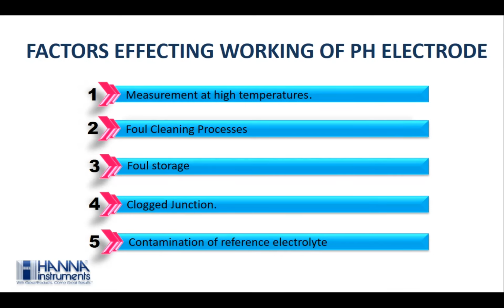Storing the pH electrode in distilled water is the biggest misconception people have. Storing a pH electrode in distilled water will result in the leaching of glass, and also the leaching of salt from the reference electrolyte into the distilled water, as distilled water is a very aggressive solvent. It is just like storing a fountain pen upright; it eventually stops working. Storing without any storage solution will dry out your electrode, resulting in high errors in readings as the outer hydrated layer is not present.